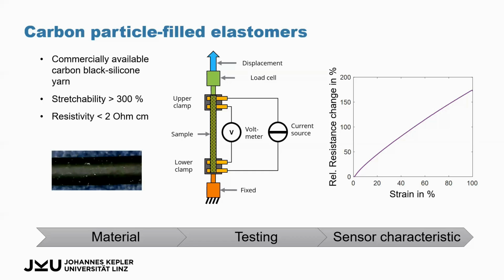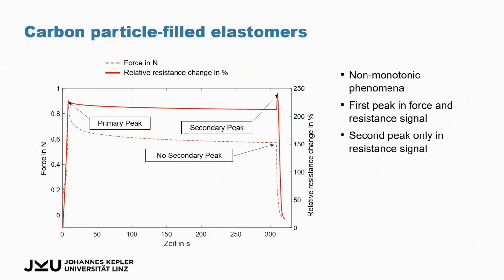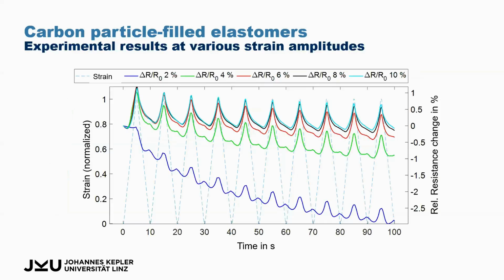And there we can see a very interesting phenomenon: if you strain the material, then keep the strain and relax it again, in the force signal you can see this relaxation, right? So you get to the first peak, you have relaxation, it goes back. But the resistance increases as expected, drops a little bit due to the relaxation, but you get a secondary peak. In the electroactive polymer community, this was coined by Ian Anderson as the bunny ear phenomenon, but it's also known as, for example, the shoulder phenomenon, because you get the primary peak and then kind of a shoulder if you do cyclic testing.